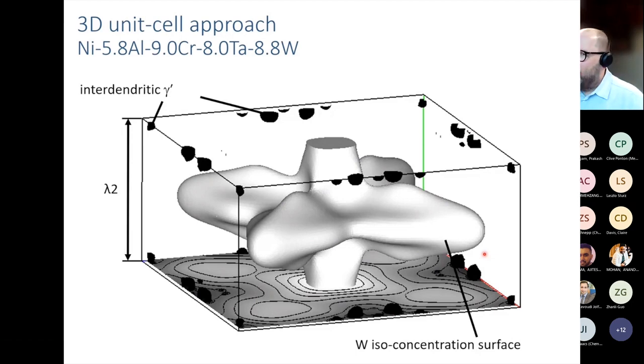Just to show off a little bit, phase field, of course, is very powerful doing 2D, but we can also move to a 3D simulation. So here we have a slice of a dendrite and its formed dendrite arms. If we look at the bottom, this is for the same alloy as in the previous slide, but this time we just look at tungsten. If we have the segregation map at the bottom, we find that here the segregation pattern is slightly more complex. And we also find that the gamma prime phases are almost like baubles on a Christmas tree hanging between the branches.